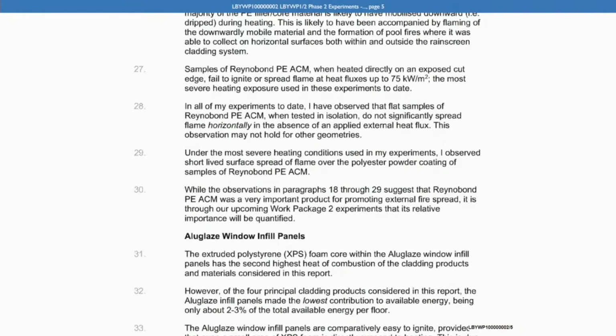And can we go to LBYWP 1702, page 5, paragraph 29. And there you say this: under the most severe heating conditions used in my experiments, I observed short-lived surface spread of flame over the polyester powder coating of samples of Reynobond PE ACM. Are you able to say what the likelihood is that there was some surface spread of flame over the Reynobond PE ACM in the early stages of the Grenfell Tower fire?